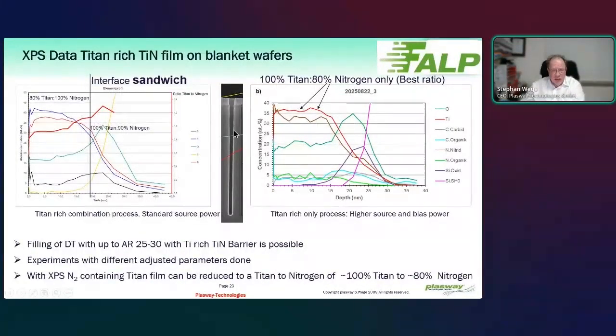Another interesting part is when you would like to fill a trench, maybe in the order of aspect ratio 25 to 30. So we can fill this complete trench with a sandwich of a titanium nitride film. And the titanium nitride film we can also play with, due to the fact that we can also etch in situ, we can play with the nitrogen to titanium ratio. So we can really create a titanium-rich film or a titanium-good barrier film. So if you would like to have a very good interface which is titanium-rich, we can play with our parameter, and we can have on the one hand a titanium-rich interface with a good conductivity, and on the other hand, a very perfect barrier film.